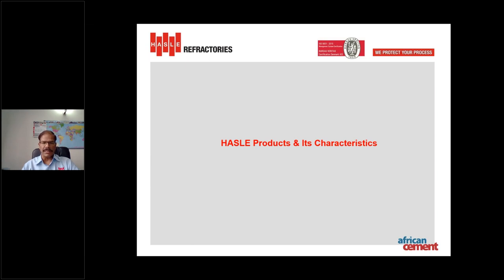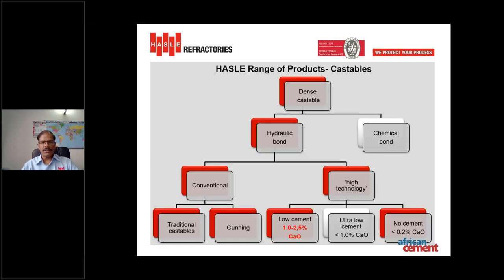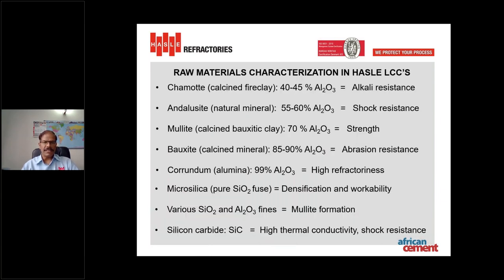Coming to the HASLE products and their characteristics. HASLE produces a variety of dense castables, like traditional castable, gunning castable, low cement castable, and no cement castable, which cater to most of the critical areas of a cement plant. The major raw materials used and their characteristics are: chamotte, used for alkali resistance; andalusite, which provides thermal shock resistance; mullite for strength; bauxite for abrasion resistance; corundum for high refractoriness; microsilica for densification and workability of the castable; other silica and alumina fines for mullite formation at elevated temperatures; and silicon carbide for high thermal conductivity and shock resistance.